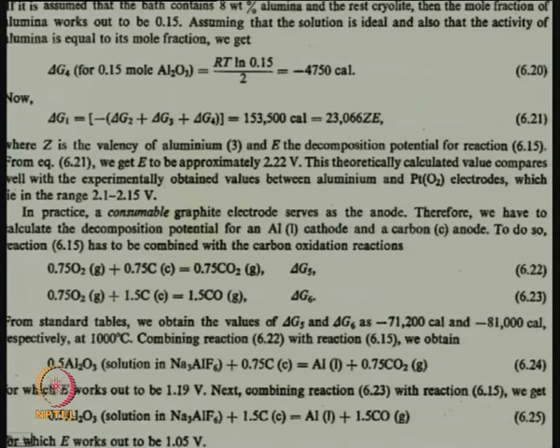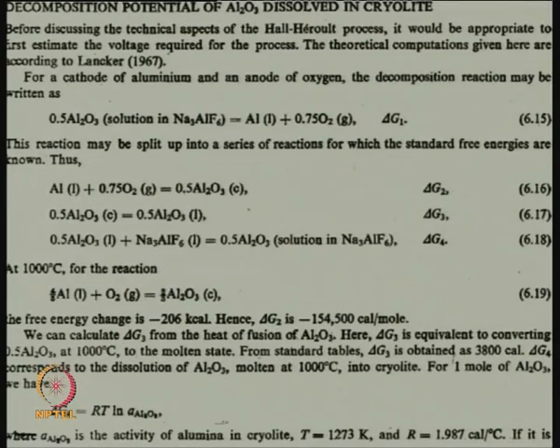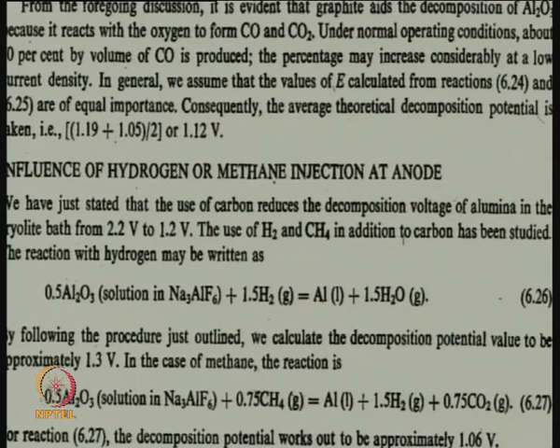Okay. Now, what we have today is this process where you have a graphite anode and a graphite bottom layer as cathode. From the foregoing discussion, it is evident that graphite aids the decomposition of Al2O3 because it reacts with oxygen to form CO and CO2. Under normal operating conditions, about 50% by volume of CO is produced. The percentage may increase considerably at low current density. It depends on current density also. In general, we take an average of the values calculated from these two reactions. So, the theoretical decomposition voltage using graphite electrodes comes to 1.125.